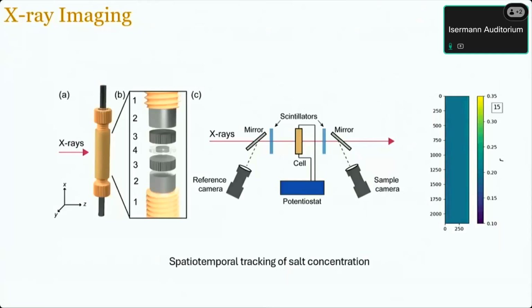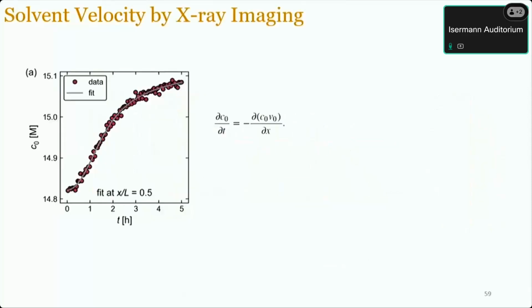The last bit of the puzzle I want to say is that now I have a student, Emily Abdo, and she can do this thing. This is the concentration as she's polarizing, using X-ray imaging. It's sort of crazy, right? I mean, you take the cell, you go to a synchrotron, you take a measurement. The salt scatters X-rays like crazy. The polymer doesn't. So wherever there's high scattering, you have high salt concentration. And this is quantitative because the scattering cross-sections are all known. So there's no approximation. And so you can sit, for example, in the middle of the cell and see how